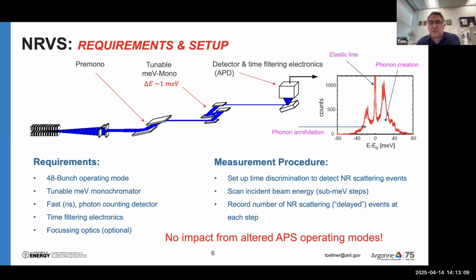So 76 nanoseconds between pulses is actually a benefit in the case of iron 57. There's something like a 20% gain in the signal rate, because the time average excitation or decay rate is higher, simply because the pulses are not too far apart. So there's a little bit of benefit there, actually, in the case of vibrational spectroscopy.